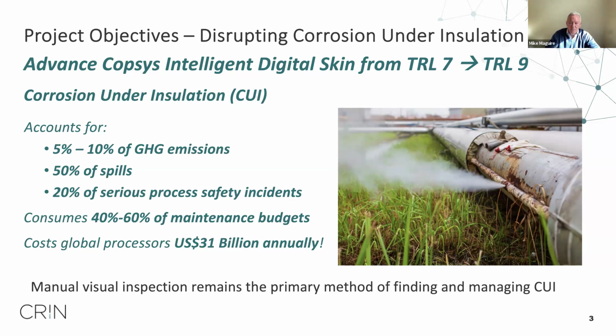And then when it stays there for a prolonged period of time, up against the coating, which is the last line of defense, it's not a matter of if, but when the water eventually finds its way through the polymer matrix of the paint to the surface of the pipe, and eventually that paint fails. And when it does, you get an area where you've got a huge amount of electrochemical potential energy focused on one small spot, and you get pitting corrosion that will go through the wall of a pressure containing piece of equipment like pipe in a matter of months. Then you can wind up with a non-detected leak that could lead to a gas cloud or releasing some sort of noxious substance into the atmosphere, which you definitely don't want.